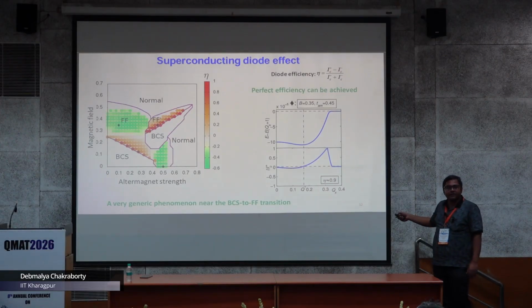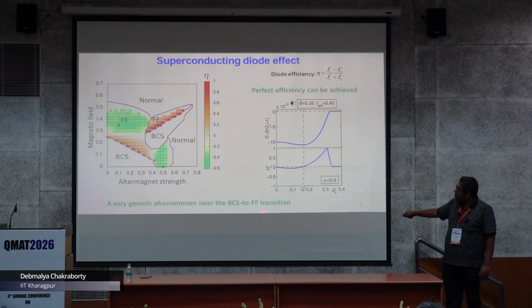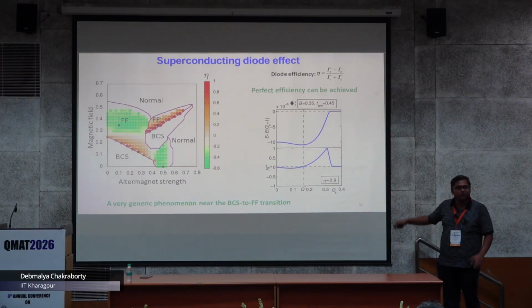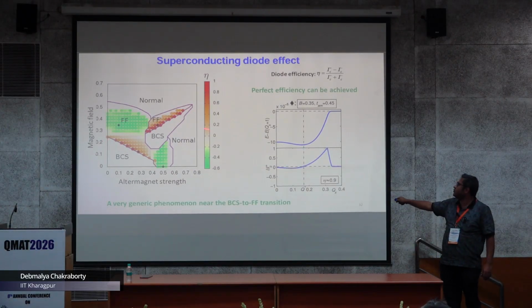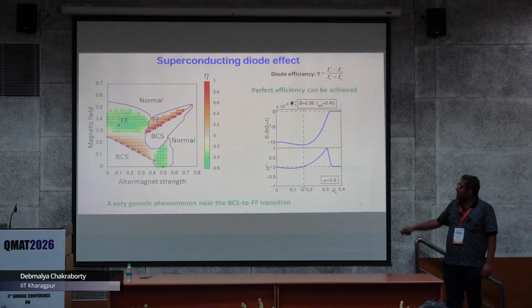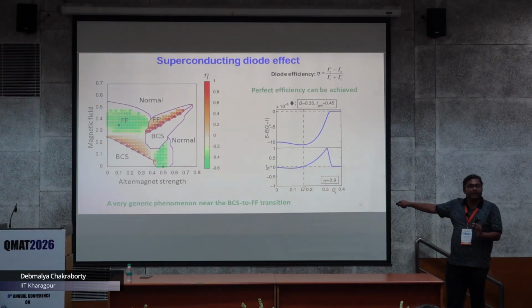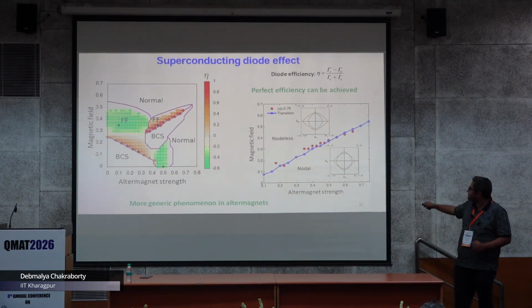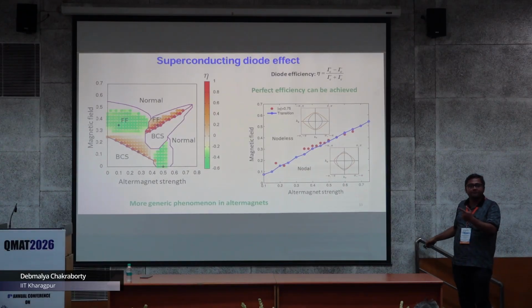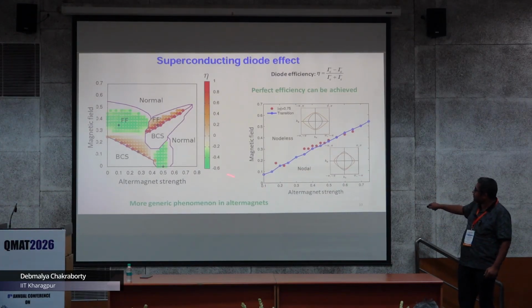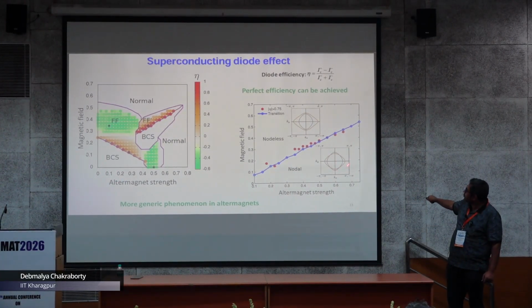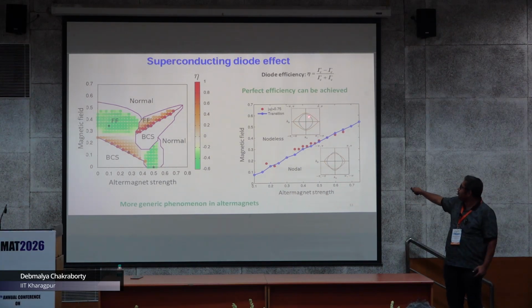It's much more interesting because it's not all BCS to FF. If you look at this BCS to FF, it's not perfect. The efficiency would be 20 to 30%. Efficiency will only be perfect if you are near a second order transition, and that happens because, as I said earlier, this structure with magnetic field actually goes from nodal to nodeless.